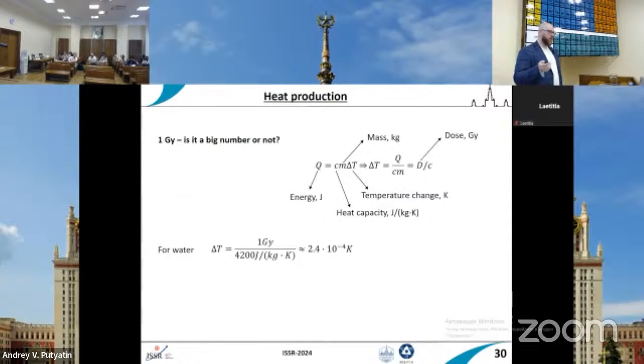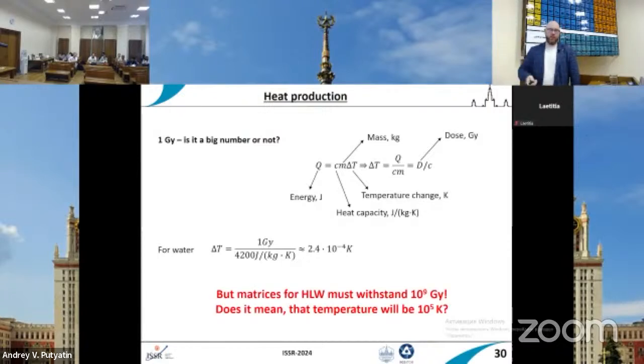But if we look at the requirements for the matrices, especially for high-level waste, we will see that modern requirements say that borosilicate glasses, for example, should withstand doses up to 10 to the 9 gray. If we multiply these numbers, that would mean that the temperature should be something like 100,000 Kelvin. But why should the temperature in our matrix be so big? The answer is that in this calculation, we assume that the whole energy goes into our material at once, in one moment.